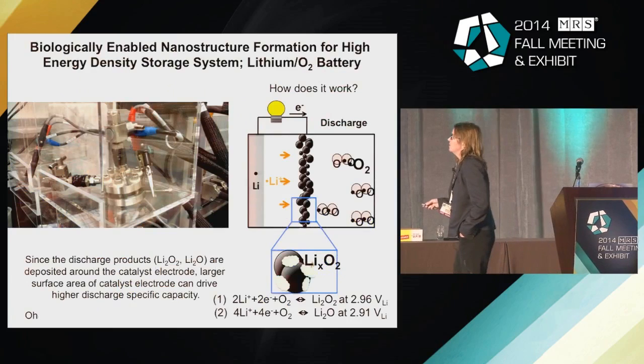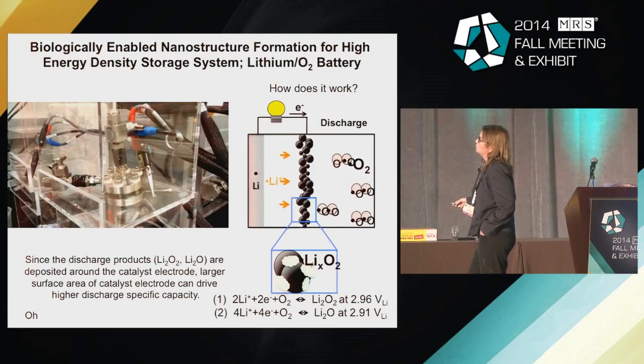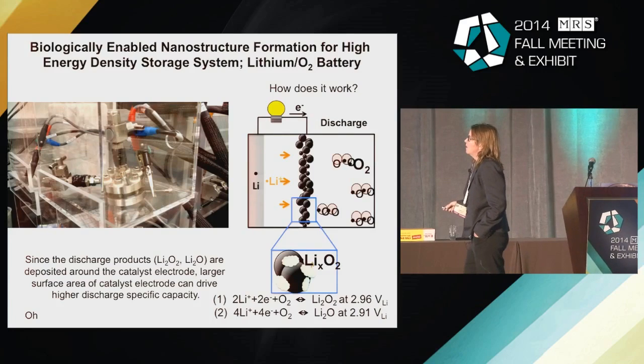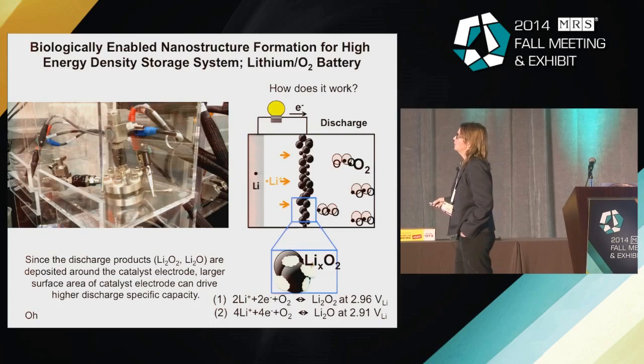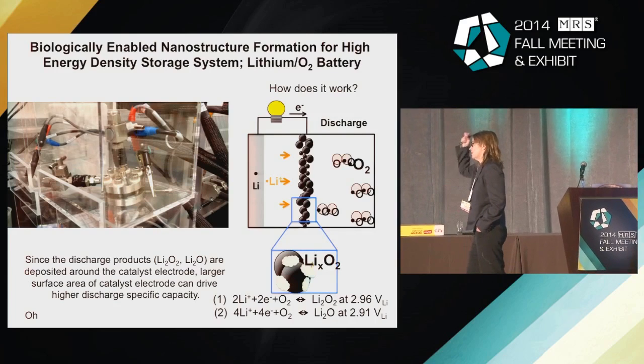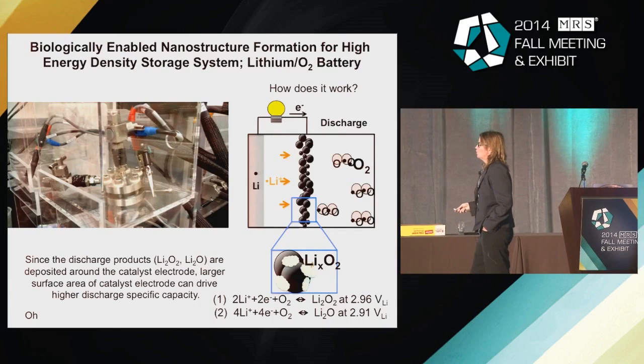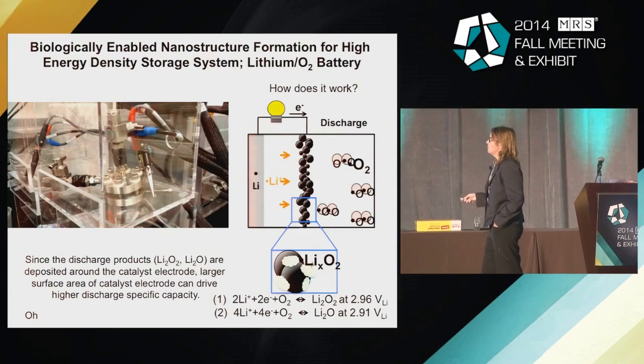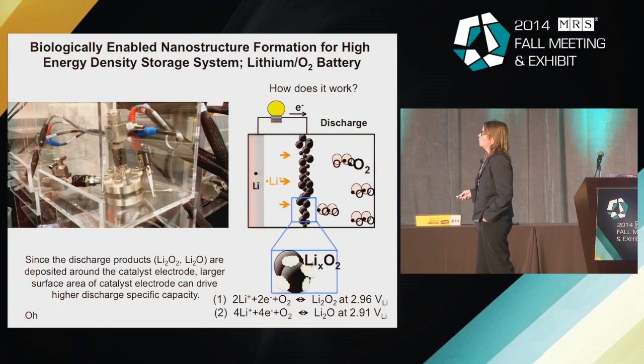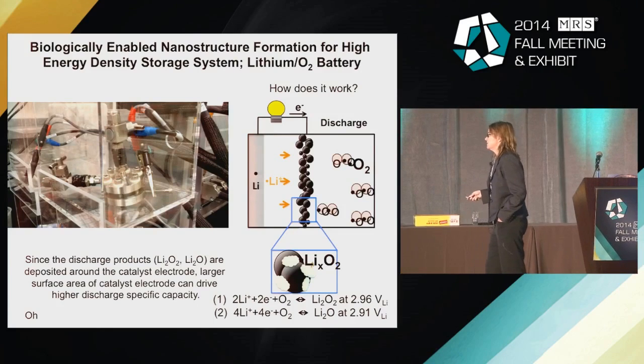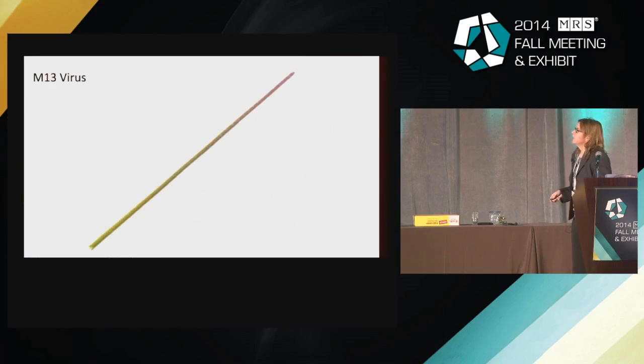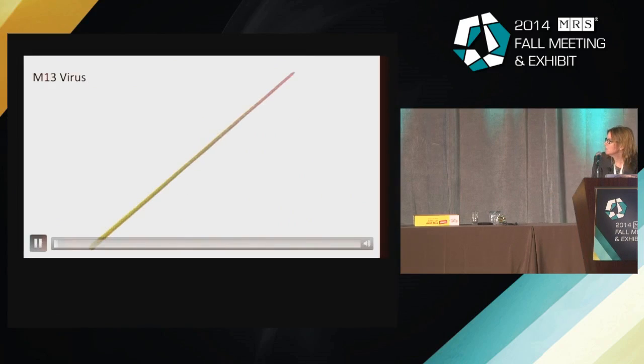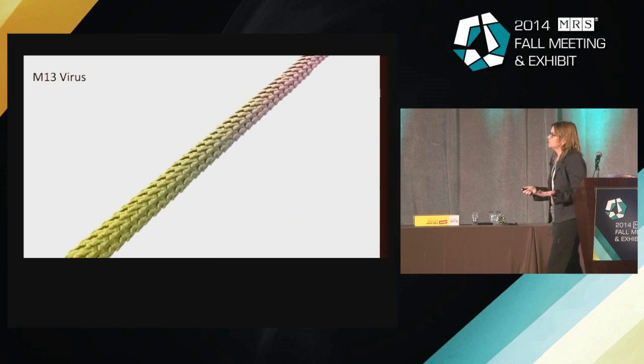And so this is work from Dahyun Oh from my group. And what she did was she genetically engineered viruses to grow materials for the catalyst electrode. And the idea is one of the problems with cyclability is that the discharge product of lithium peroxide builds up on this electrode. And so we wanted to figure out a way to both increase the catalytic efficiency as well as decrease the ability of the Li2O2 to block holes and pores so that we could actually increase the ability to cycle this material.